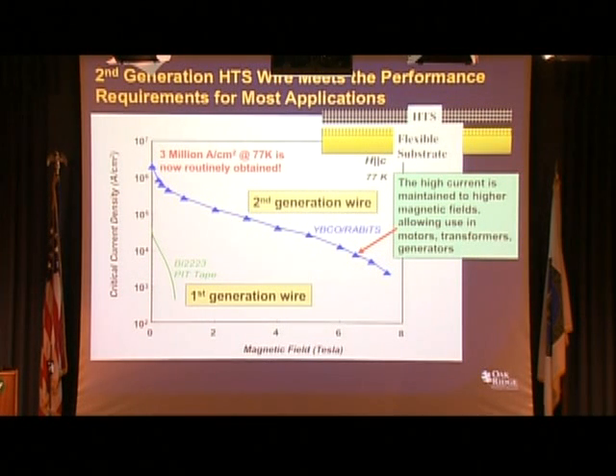So I showed you this plot in the very beginning, saying that the first generation wire technology was this green curve, and what we really wanted to be was the blue curve. And in fact, it turned out that one of the first few samples of the superconductor on this RABiTS substrate was as good as the superconductor on a strontium titanate single crystal. And today, this same curve has moved up, straight up, where you're starting at 3 million amps per centimeter squared. American Superconductor routinely fabricates kilometer-long tapes now with a starting JC of 3 million amps per centimeter squared.